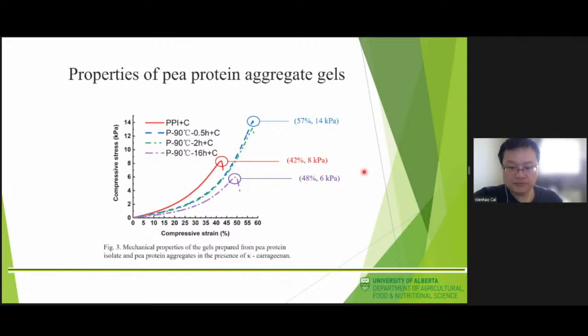Interestingly, the gel strength of the gel made by pea protein aggregates heated for half an hour and the κ-carrageenan was almost doubled to achieve a compressive strength of 14 kPa, and the compressive strain was increased to around 57% before fracture of the gel. This indicated that using aggregates instead of untreated protein could significantly improve the pea protein gel mechanical properties, making them much stronger and elastic.